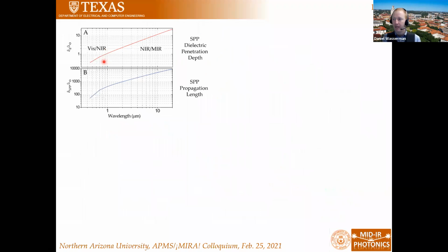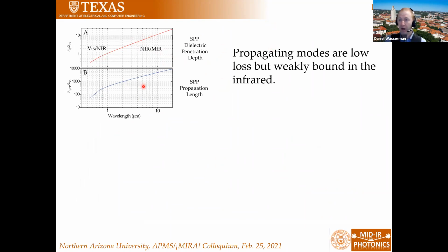But what this effectively means is that if you're trying to support a plasmonic mode, for instance a propagating wave on a metal dielectric interface, it can propagate for a long distance. The reason is that it's not tightly bound. This is the penetration depth into the dielectric, and you can see that the penetration depth of the surface mode is on the order of between 1 and 10 wavelengths. So this is not a subwavelength mode. You're never going to be able to go nano with a traditional metal dielectric interface in the mid-infrared. You have long propagation lengths, but that's because you're not really interacting with the metal. You're not tightly bound to that metal.